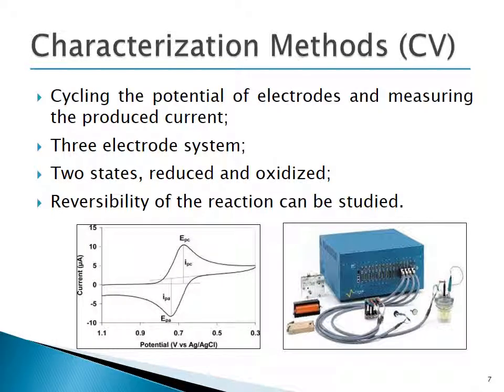Now, the different characterization methods. Cyclic voltammetry is used to analyze the electrode-electrolyte system in a well-defined potential window. It uses three electrodes: reference, counter-electrode, and measurement, and it cycles the electrode's potential and then measures the produced currents. When we apply the potential, electrochemical reactions occur, and the analyte is reduced and oxidized. In this particular case, the CV response is affected by some features, such as geometric area and roughness of the electrodes.